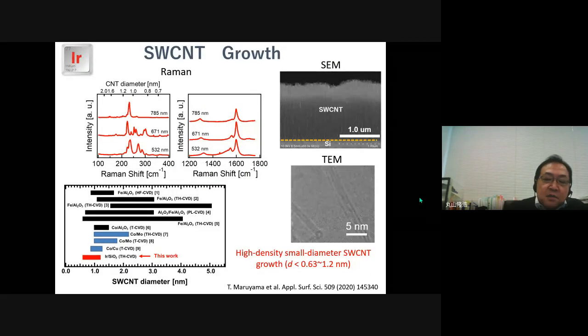We also performed single-wall carbon nanotube growth by ACCVD using iridium catalysts. Raman measurements showed that, like platinum catalysts, SWCNT diameters were distributed below 1.1 nanometer. It should be noted that vertically aligned single-wall carbon nanotubes, so-called nanotube forests, were formed on SiO2 silicon substrate. This means that iridium catalysts are highly efficient to grow single-wall carbon nanotubes.